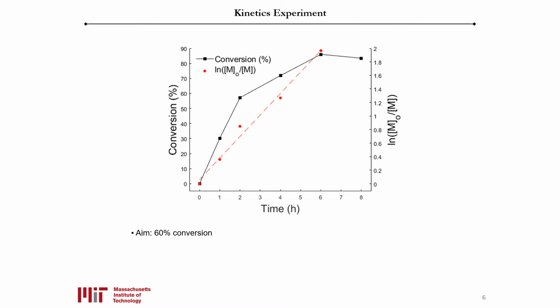After the polymerization was verified, a kinetics experiment was performed. We aimed for a specific molecular weight or percent conversion. We aimed for a 60% conversion due to wanting low dispersity within the polymer. If we were to aim for a higher percent conversion, such as 80%, we would risk bimolecular coupling.